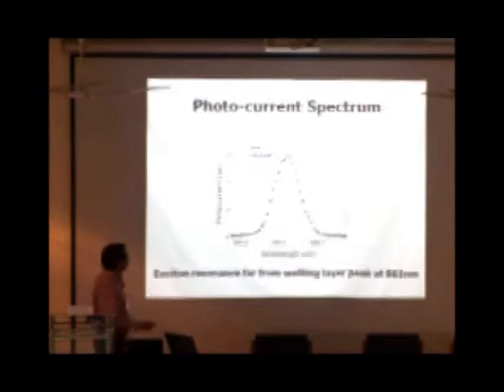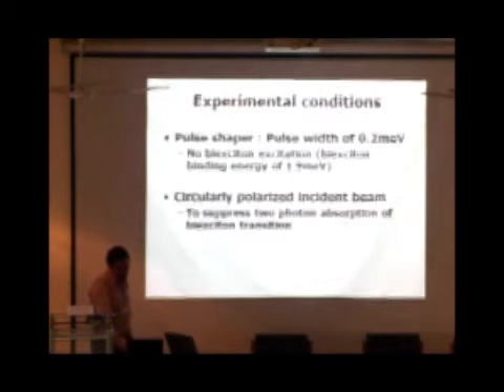So this is a photocurrent spectrum. As you sweep your incident light wavelength, you see essentially a peak. The peak matches with the exciton resonance because you have maximum absorption.